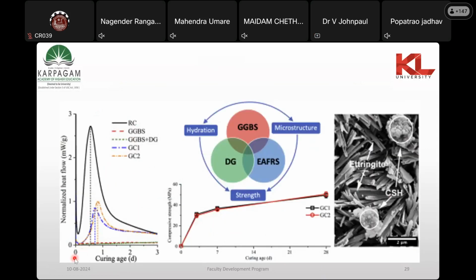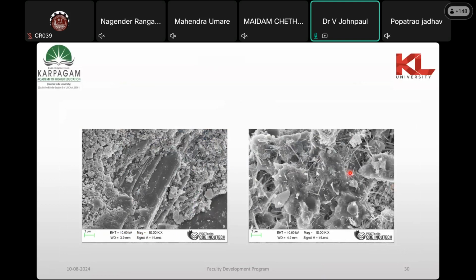Then curing age, normalized heat flow. If you just look into this also, GGBS with curing results, heat flow is very less compared to the normal. Just look into the images. There is a formation of ettringite and CSH, calcium silicate hydrate. You can see through the images. In the next picture, I'll show you clearly that the left one,